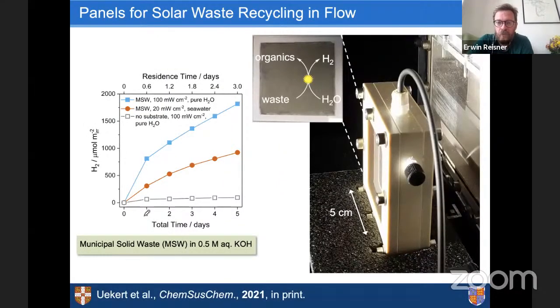Also here we are going towards continuous flow. So if we found maybe always centrifuging off our particles, reusing is not the most efficient. And we also need to think about processing much more. And for continuous processing, really flow, I think, is the way forward. And what we've done here is you can simply deposit your light absorbers, your carbon nitrides on, in this case, glass panels. That's an example with 5 times 5 centimeter. You integrate them in a little flow device, and then you constantly pre-treat your polymer solution, purge it into your flow reactor, break it down with sunlight, and purge it off. And essentially, you just keep your panel intact. And once it's being degraded, although you have not reached that point, you can just replace it with a new panel, hopefully recycling the old panel.